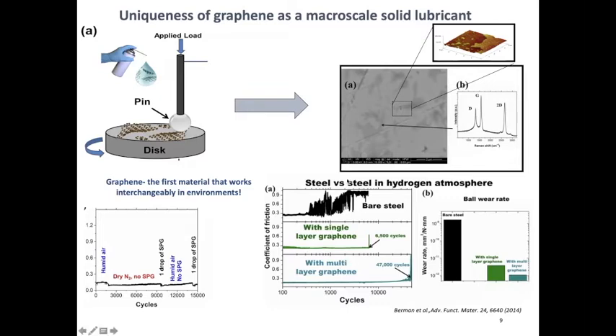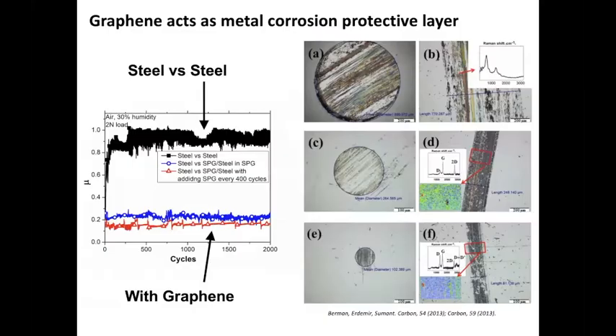We tried to compare our sporadic flakes, we call it multi-layer graphene, but it's not really multi-layer because you have several layers only at some places, to just single layer graphene, which was CVD grown and then transferred onto the steel substrate. And with this multi-layer graphene, our low friction behavior was significantly extended. Why is it happening? Because with this overlapping of the flakes, they have more mobility during the sliding to rearrange and provide easy shearing of the surfaces. So let me show you how it goes. Here at the bottom, you can see the wear of the systems when they are protected with the graphene surfaces.